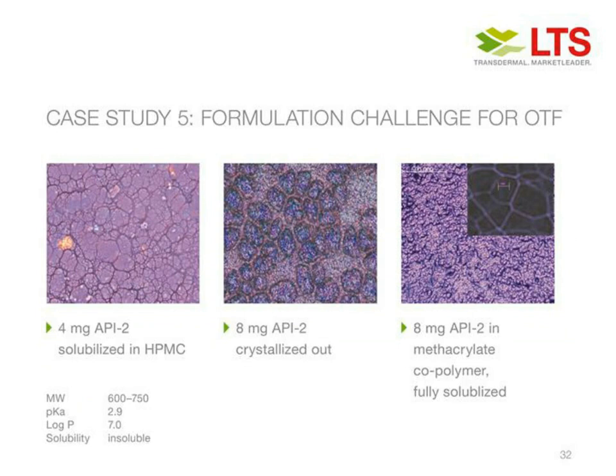So finally, with case study 5, just to give you a sense of some of the formulation challenges, one of the key things with oral thin film is the challenge of recrystallization of the API. Some of the formulations could be a solution form or an amorphous form, and of course, if you have it in the amorphous form, you expect a faster onset of action, but there is a downside to that: it depends on the drug solubility itself, and sometimes it precipitates out.